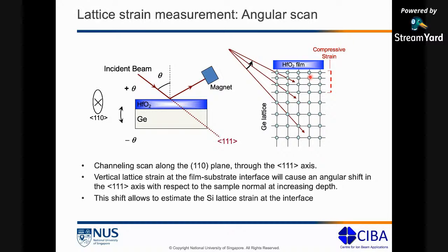So that means that when we deposit these kind of thin films on these single crystal lattices, we want to know the amount of strain you have in this lattice. And also, we want to know whether that strain is compressive or tensile, right? So there is a need to find out what kind of strain there is and the amount of strain. And that is where ion channeling and RBS becomes very useful, because I believe they are one of the only techniques, or one of the most used techniques, where lattice strain can be quantified. So let's see how this works.